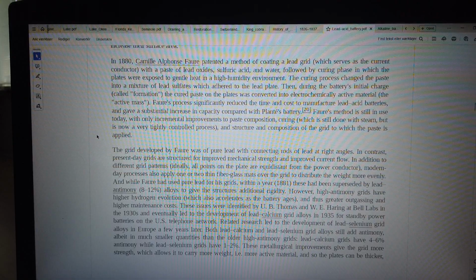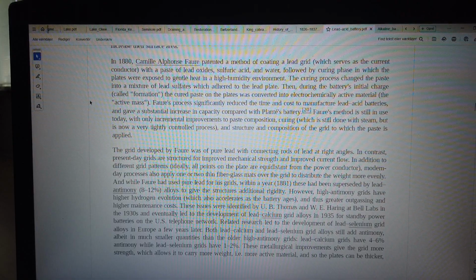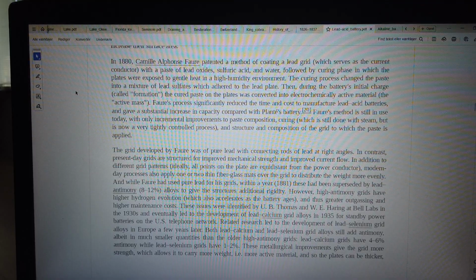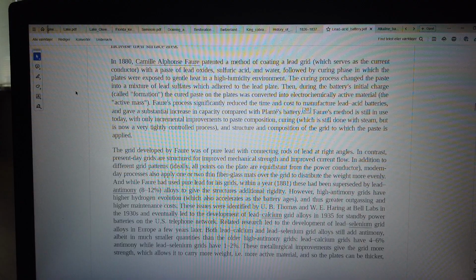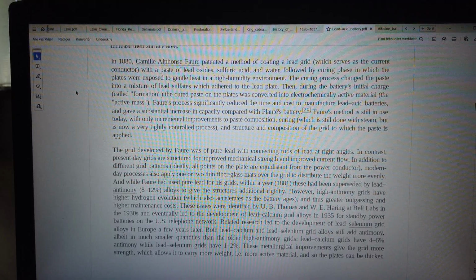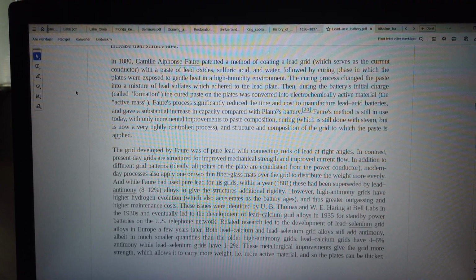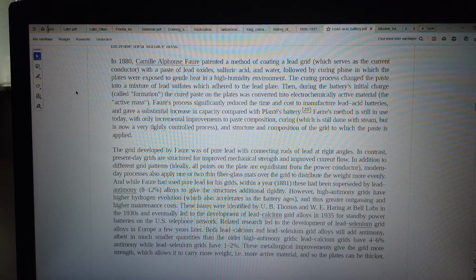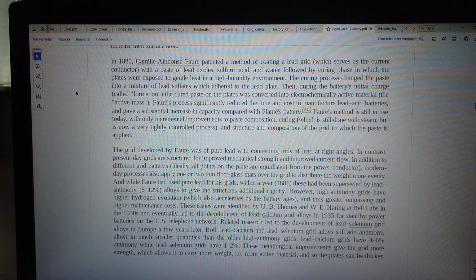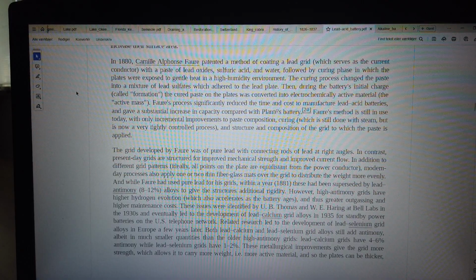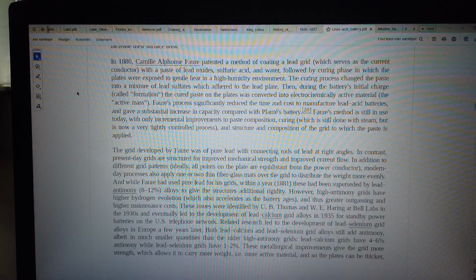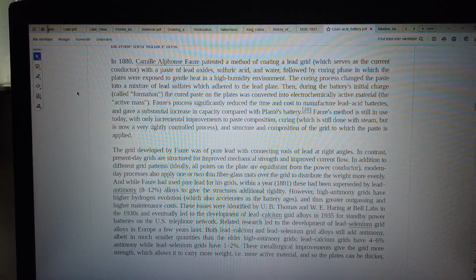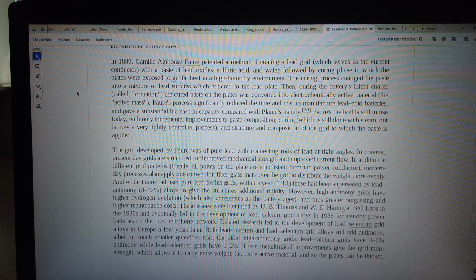However, high antimony grids have higher self-discharge via hydrogen evolution, which also accelerates as the battery ages, and thus greater outgassing and higher maintenance costs. These issues were identified by U.B. Thomas and W.E. Haring at Bell Labs in the 1930s and eventually led to the development of lead-calcium grid alloys in 1935 for standby power batteries on the U.S. telephone network. Related research led to the development of lead-selenium grid alloys in Europe a few years later. Both lead-calcium and lead-selenium grid alloys still add antimony, albeit in much smaller quantities than the older high antimony grids. Lead-calcium grids have 4-6% antimony while lead-selenium grids have 1-2%.